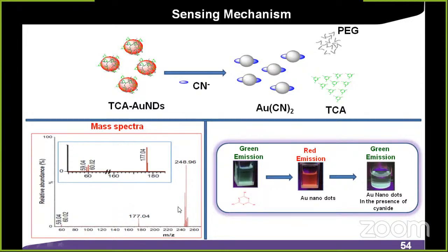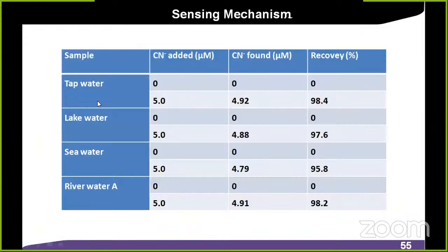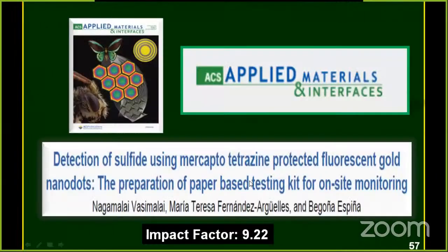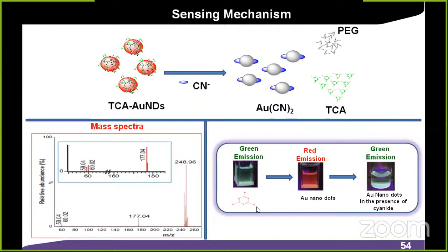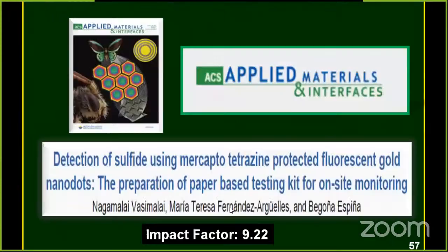Then we confirmed with mass spectrum. So these are all the peaks for gold cyanide, and these are the ligand peaks. And we used tap water, lake water, and sea water as real sample analysis. We got good recovery. Then the second work we published in ACS Applied Materials and Interfaces. Actually, in the previous paper, I bought this TCA commercially from Sigma Aldrich. But in this ACS paper, I synthesized the ligand by myself.